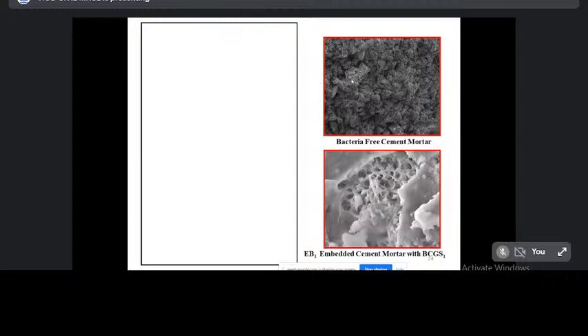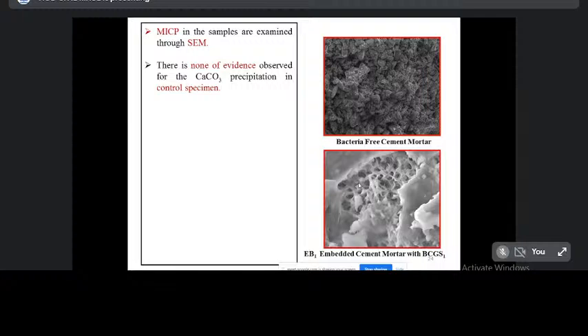Next, we move to the SEM image. The first slide shows the control specimen SEM image. Then the second photo shows the SEM image of the Enterobacter embedded cement mortar specimen. Here are the observations. MICP in the samples is examined through SEM. No evidence is observed for calcium carbonate precipitation in the control specimen. In the control specimen, there is no calcium carbonate.